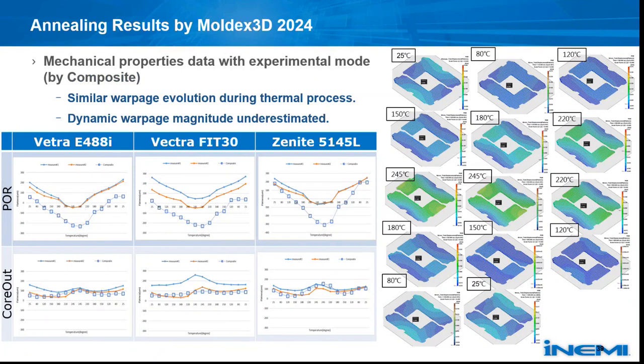Okay, so here is the dynamic warpage shift. A similar trend was observed for the high temperature warpage shift for the composite model. Here, the 2 solid lines represent the measurement data from the experiment, and the dark line represents the modeling prediction by the composite model. The overall dynamic warpage trend predicted was in good comparison with the experiment. The surface shape shifts from one type at room temperature to another when it is heated to the high temperature. But the composite model consistently underestimates the warpage value at each set temperature point, and the underestimated values are different for the material and the circuit design. Next.